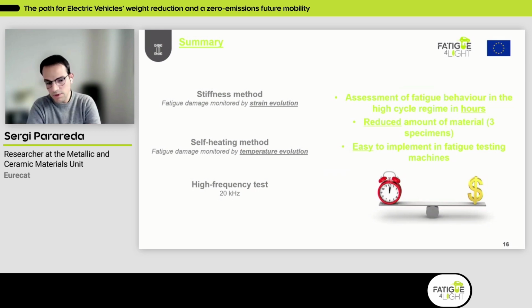And just to summarize and have an overview of all the work that we did, and to have the main ideas of these new methods, we have these 3 different methods. This is the stiffness method based on the strain evolution, pretty simple to apply in the lab, simply by monitoring the strain in the specimen. Then we have the self-heating method, also very easy to apply in the lab by using thermocouples and monitoring the temperature evolution in the material. And finally, and especially to analyze this very high cycle regime, we can use these high-frequency tests to obtain the data at a very high number of cycles.